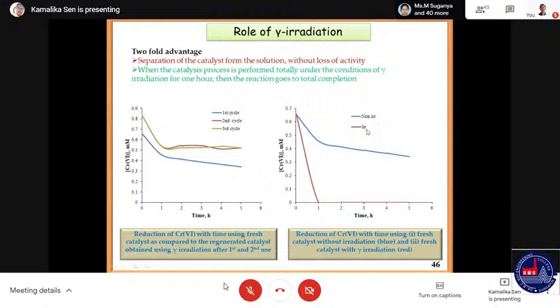After first cycle, after second cycle, after third cycle, its efficiency decreases. But if we compare it with the irradiated sample, if we take the chromium-6 solution, add the palladium quantum dot and put it in the gamma chamber, take it after some time, we will see that the reaction has gone to completion. The whole of chromium-6 has been reduced, as well as the palladium quantum dot has settled down to the bottom. So we can regenerate our costly palladium nanoparticle after the use. So it is yet another application of gamma irradiation.